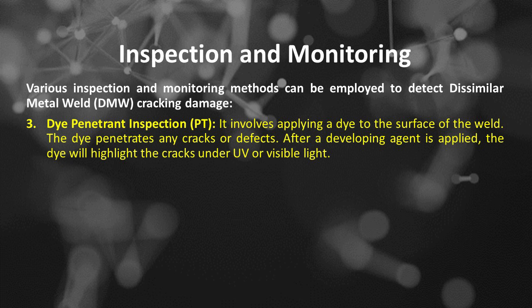Number 3 is dye penetrant inspection, or PT. It involves applying a dye to the surface of the weld. The dye penetrates any cracks or defects. After a developing agent is applied, the dye will highlight the cracks under UV or visible light.